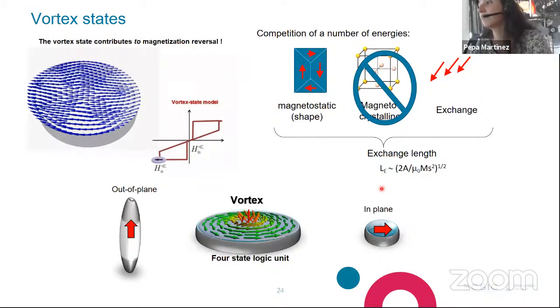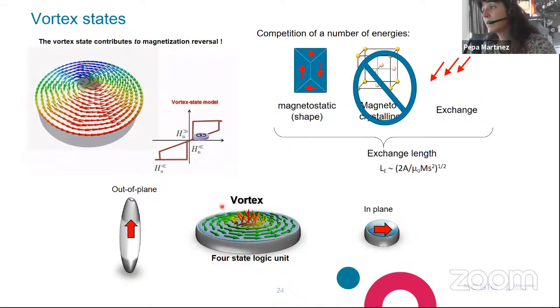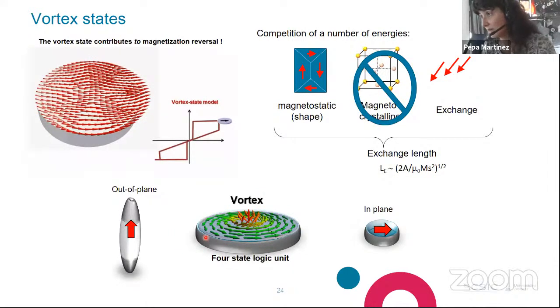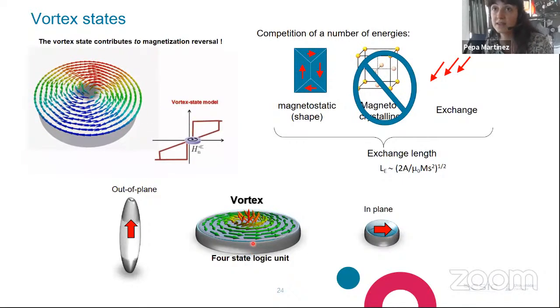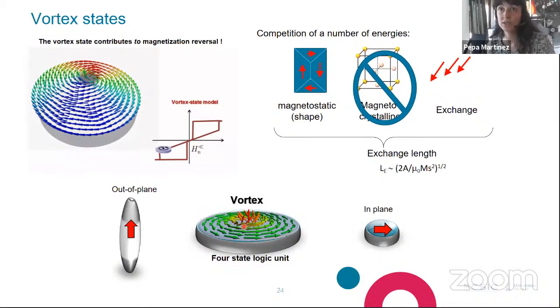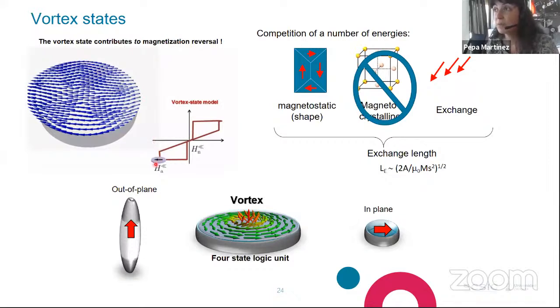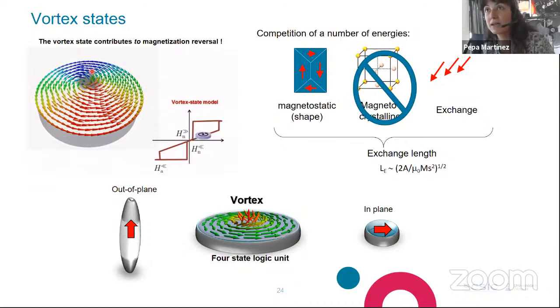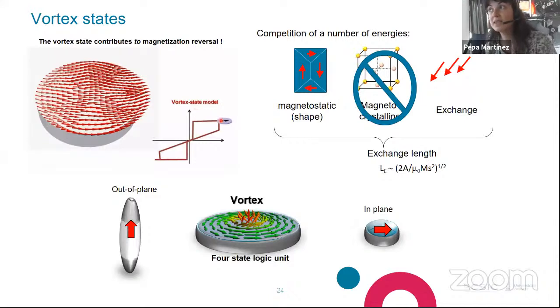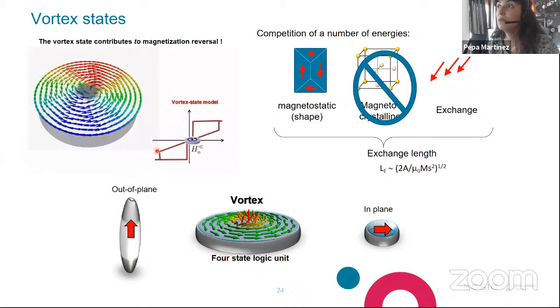What happens in between for a, let's say, mesoscopic, almost two-dimensional object? Well, usually what appears is a magnetic vortex, in which magnetic moments curl around the boundaries of the disk and point up or down in the center, okay, in order to satisfy also the exchange energy. These vortices do contribute also to magnetization reversal, as you can see in this video here. If your particle is saturated, for instance, at negative fields, and you reduce the field, at some point the vortex will be nucleated. Okay, this vortex will move depending on the direction of the applied magnetic field, up to the point where the particle is saturated, and then back, and another vortex will be nucleated and move through the particle, okay?